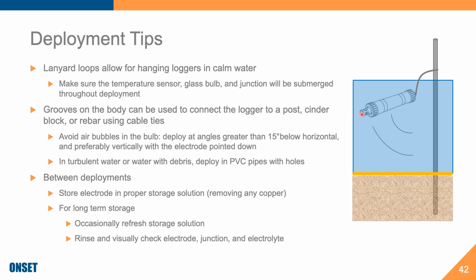And then if this is being deployed in non or slow moving water, not in sediment, then you'll want to consider using cable ties. So with our pH electrode, we have grooves on it, and this actually allows the user to mitigate the potential of flow by attaching the logger to the rebar. And it's really important to consider deploying it at an angle greater than 15 degrees below horizontal, because if it's not at 15 degrees below horizontal, you could potentially get air bubbles in the glass bulb, and the air bubbles will affect your readings. So another thing to keep an eye on when you're about to redeploy your logger is to make sure that the pH bulb has no air bubbles in it.